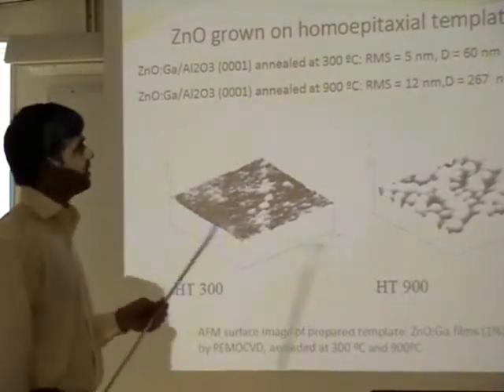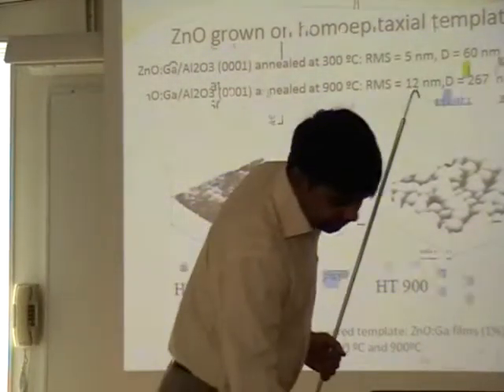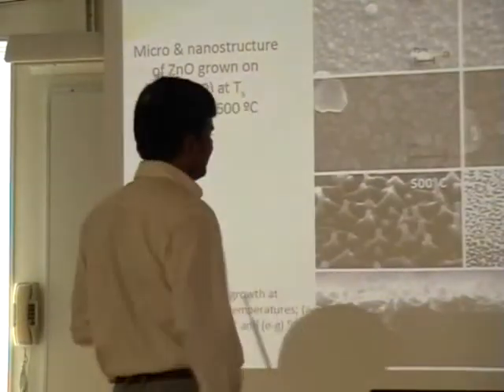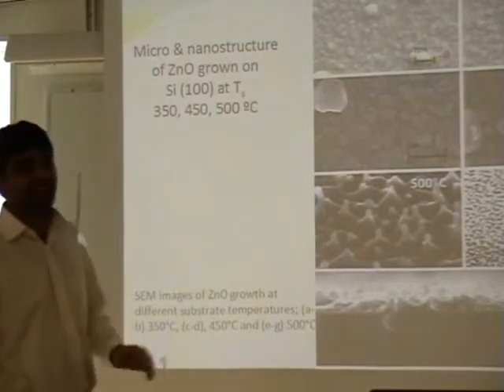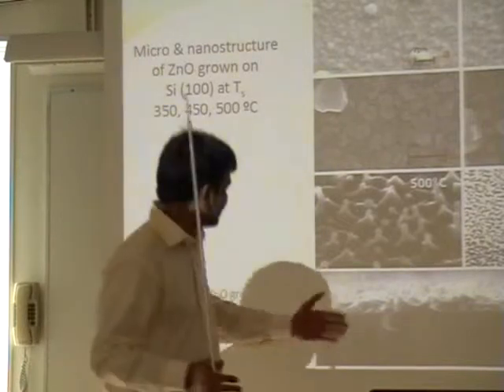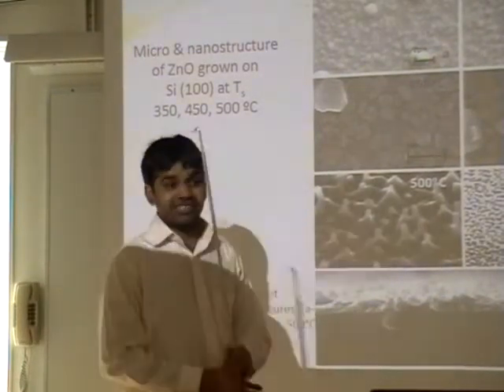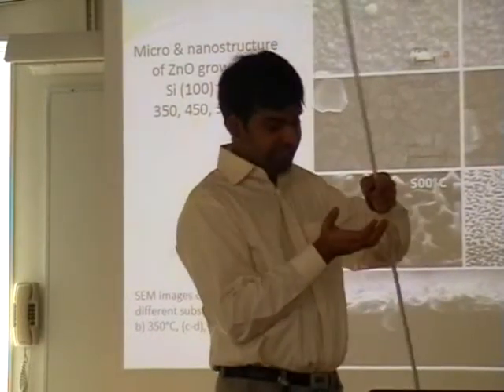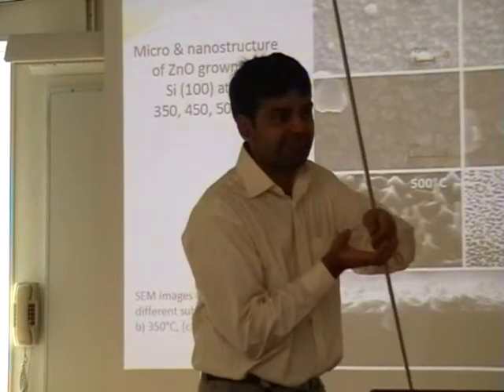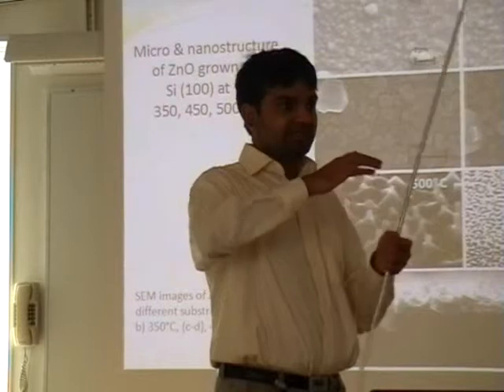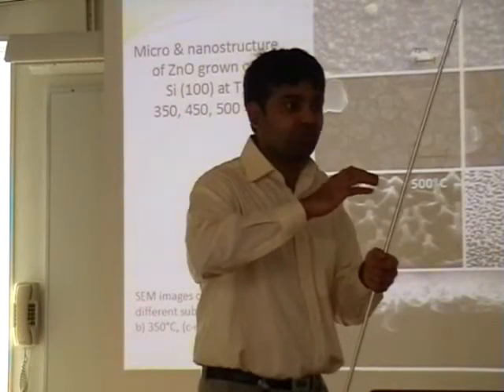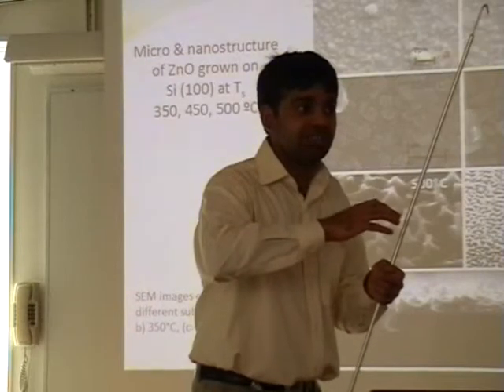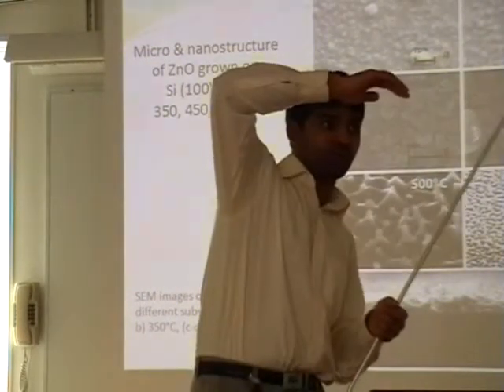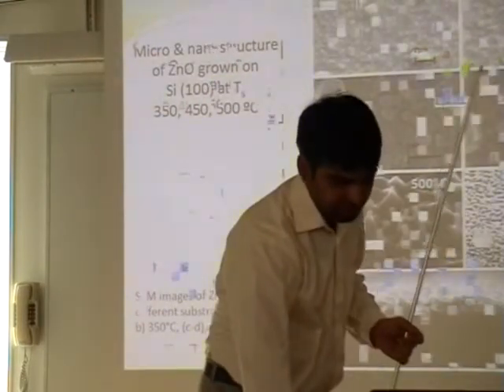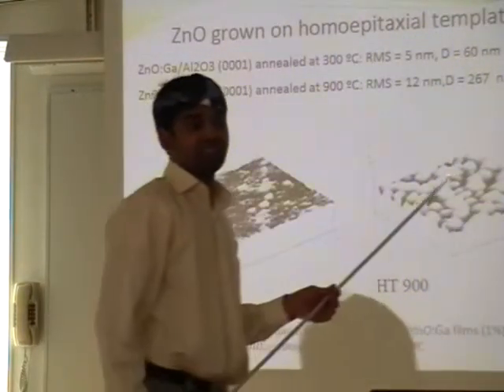Here, the second sample. I already told you during the first sample, unintentionally we got a good result. Here you can see, unintentionally. But after the other sample, we got an idea. So we made a homoepitaxy template. Homoepitaxy: first zinc oxide with gallium doped 1% is grown, then annealed, then again grown on a zinc oxide, so that we want to get a better result.